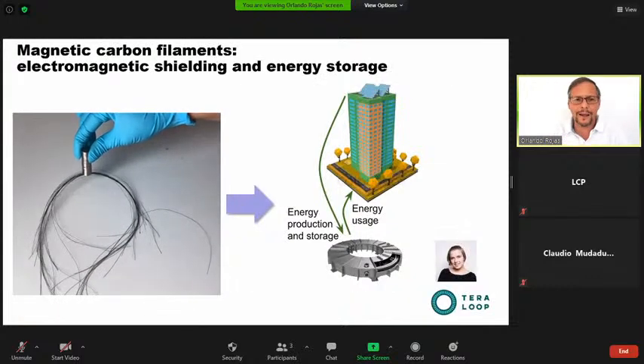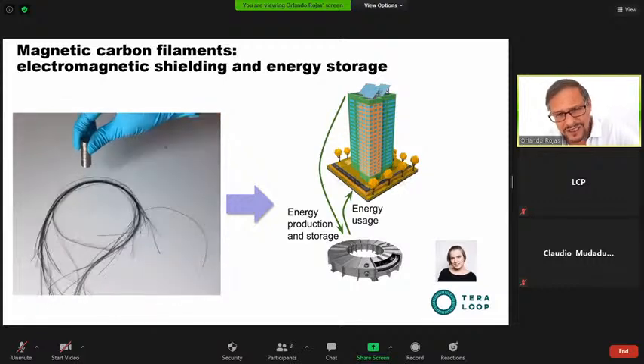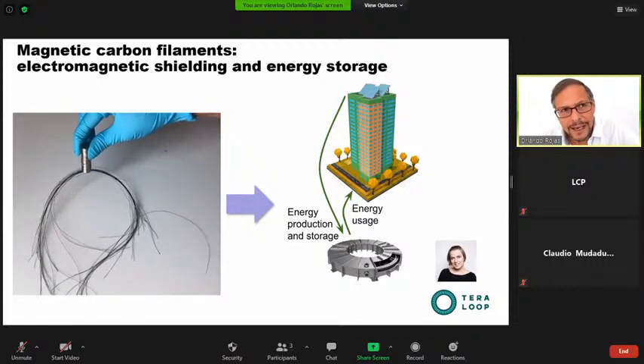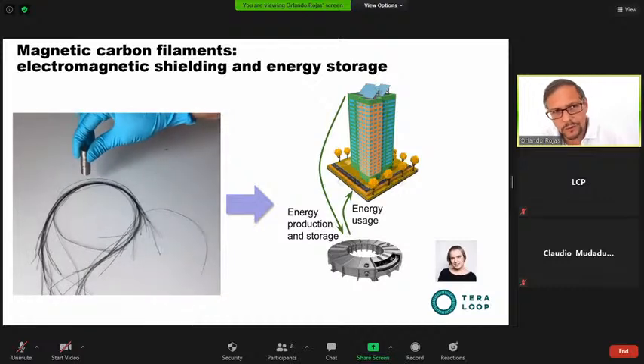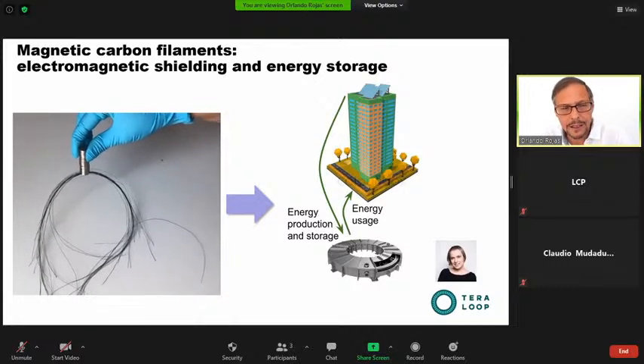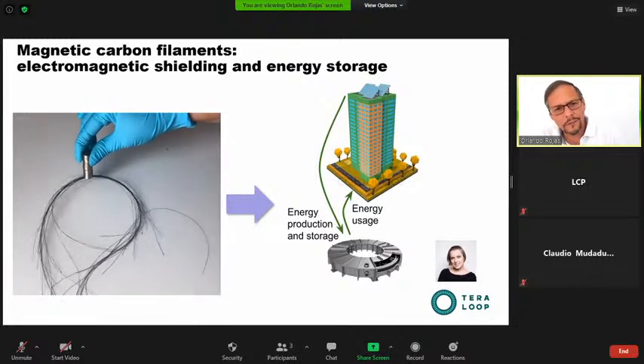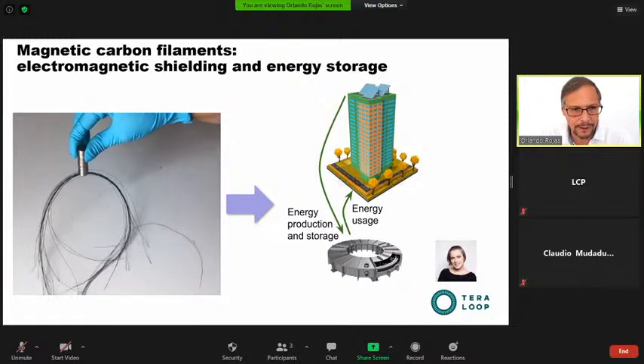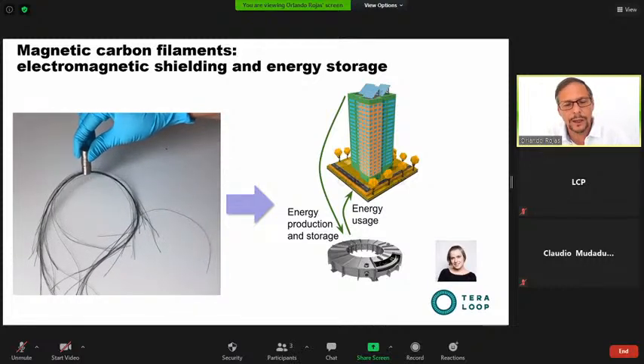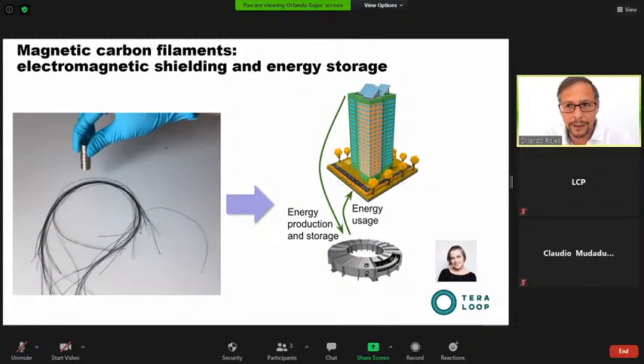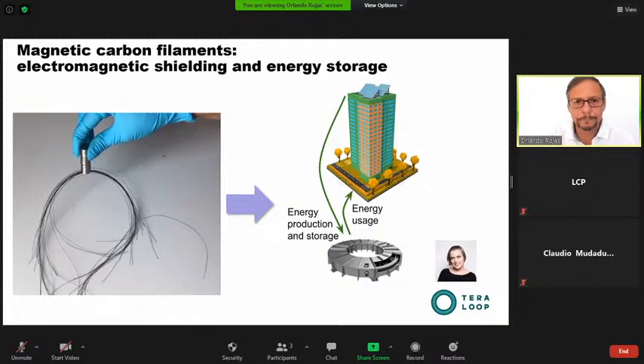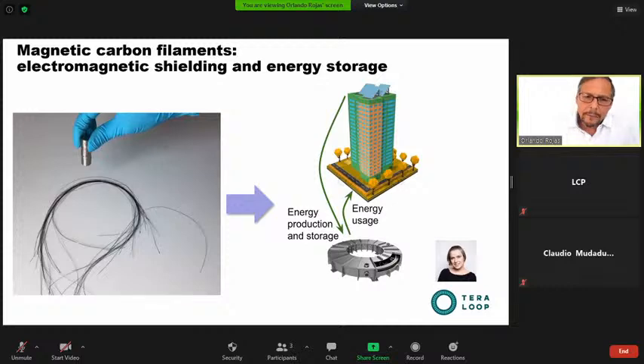This is why I like wet spinning, because it's a very unique approach, so that in the dope that we use for the spinning process, we can load particles, in this case magnetic particles, therefore making the final filament not only conductive but also magnetic, as shown here by Mary Lundahl, in the bottom right. To me, this is very important, because I think wet spinning is one of the ways that we can produce advanced materials. And here we're talking about the high value material propositions that I introduced at the very beginning.